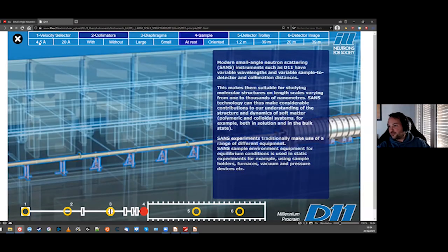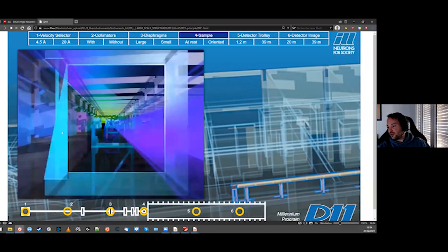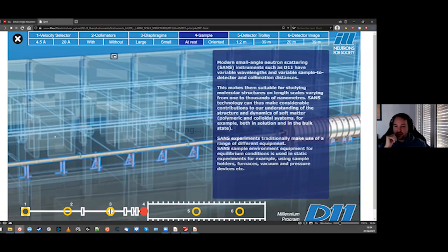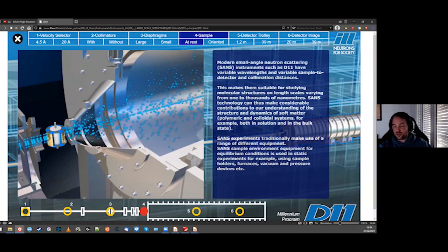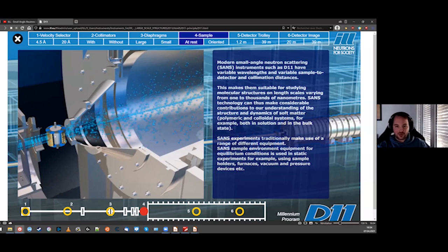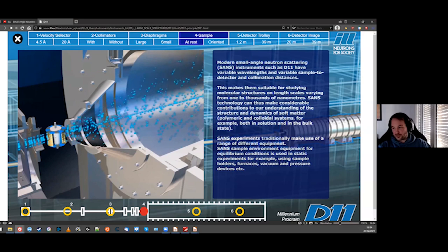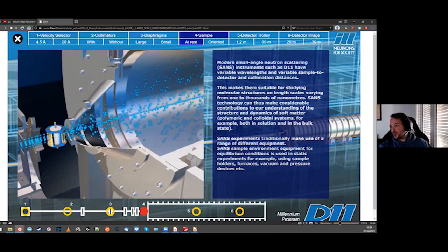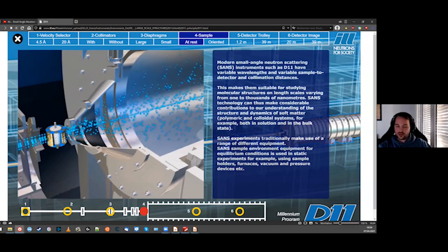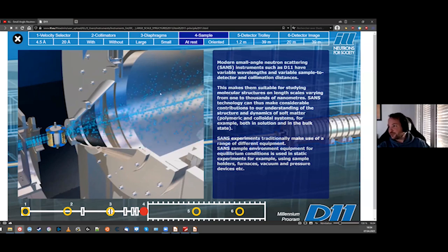Samples can be either fixed, but then we have maybe some problems, because if our sample is not isotropic, let's say rods, if we look at the rods from the side or from the top, in one way it will be a line and the other a circle. So we could see different things. Sometimes we want to see those. Sometimes we can also just rotate the sample so we have an average. We can force the sample into a specific orientation, either via mechanical or magnetic ways.